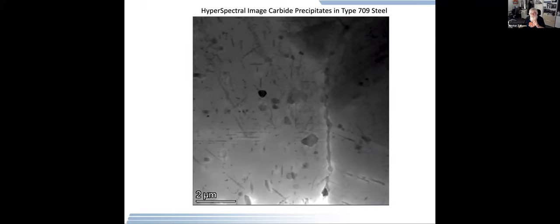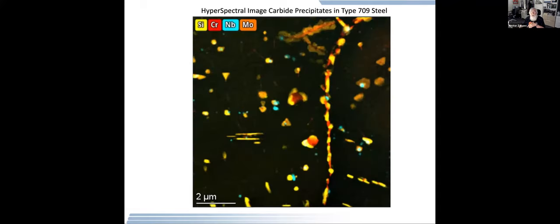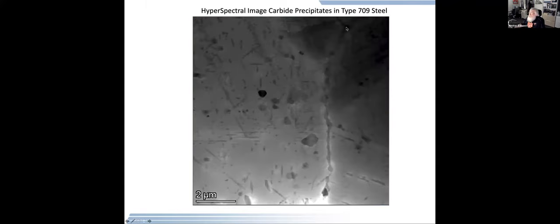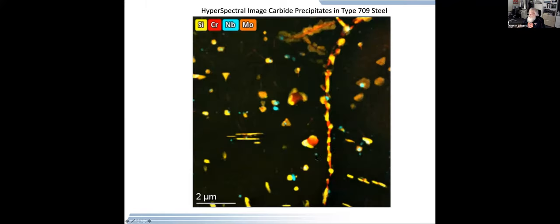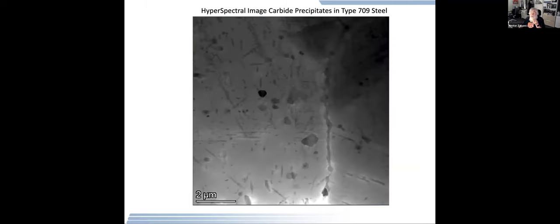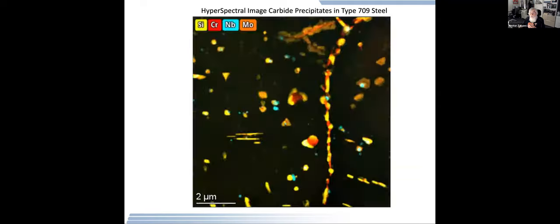On the other hand, if I make use of not only the elastic scattering, which gives rise to this image, but the inelastic scattering, I can take that image and look at the secondary information that's generated by the inelastic scattering events. Now, if I go back and forth, I can see that this series of grain boundary precipitates are silicon carbides, silicon and moly carbides. We see chrome carbides in it. We see small niobium precipitates in it. All of that helps us when we go back to look at the overall microstructure. So the two of these combined allow us to elucidate what's going on.